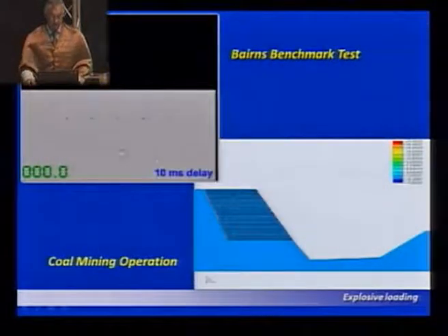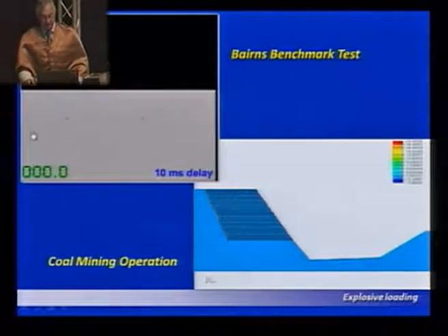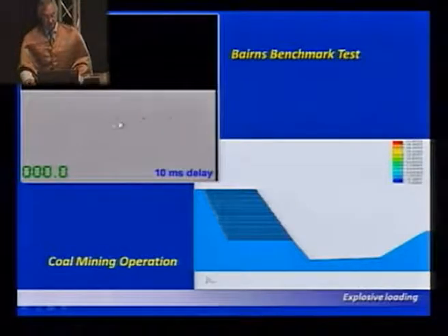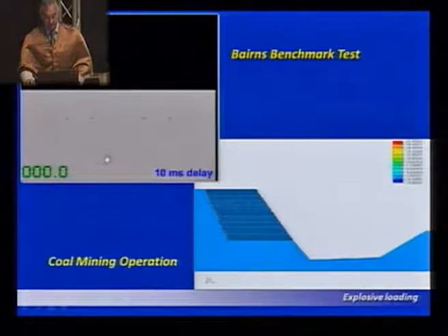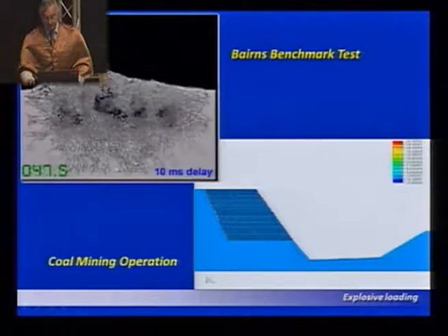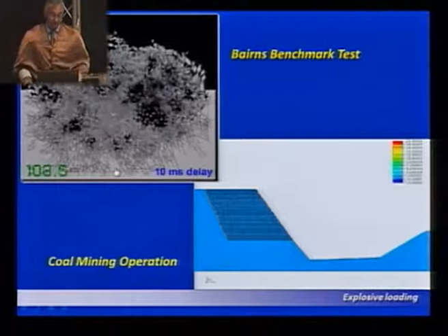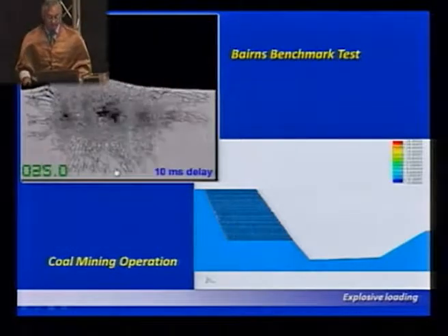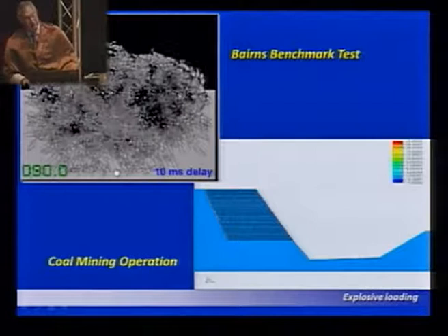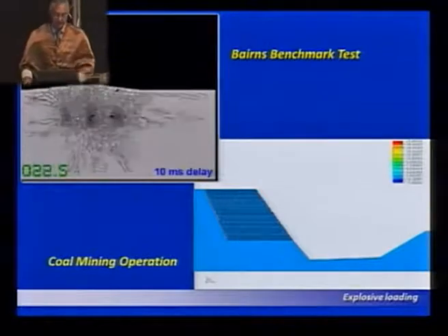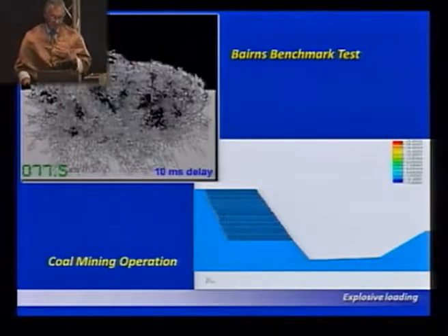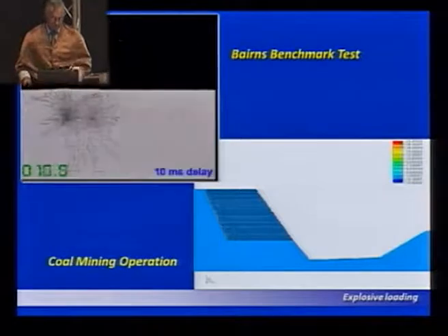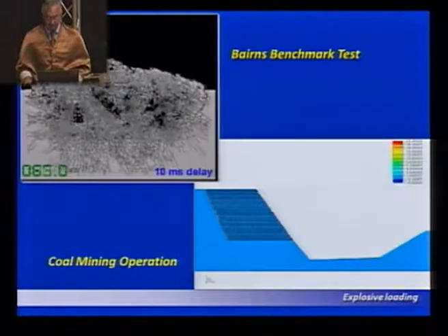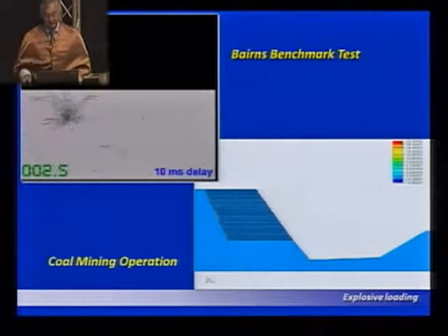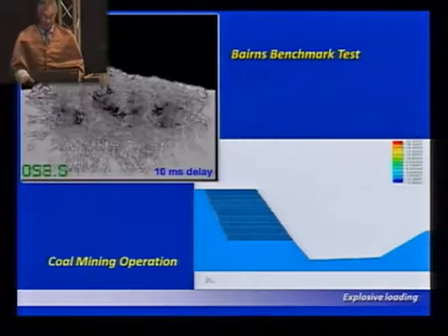Some more serious problems. This is a case of Bairn's benchmark test, where there are 5 holes here, and each contains explosive, and you detonate them with a 10 millisecond delay, and then you turn that continuum into a discontinuum. The reason why that's called a benchmark test is that the particle size distribution from the simulation is compared with what actually happened at Bairn's. And the particle size distributions, it turns out, are remarkably similar.